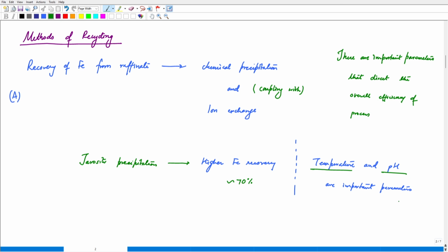A range of temperature that has been observed for chemical precipitation of jarosite that entraps iron from the raffinate solution is around 70 to 95 degrees Celsius, and pH could be in the range of 2 to 3. Now, of course, these ranges can differ, but it is seen that these are important parameters and it helps us in achieving the desired product. And of course, using this precipitate, some other valuable product can be made. So this is not the end.